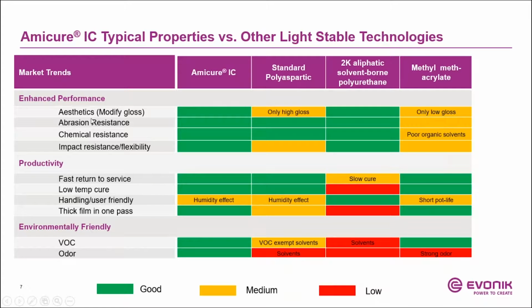So if you look at enhanced performance, one thing we talked about is aesthetics. And what we talked about here is modifying the gloss, getting the high gloss and low gloss. Polycarbamide technology, I have it in green. And in that case, because as I mentioned, you can vary the finish, high gloss and low gloss finish, similar to polyurethanes. You can do the same thing with polyurethanes through the addition of matting agents. I have the standard polyaspartic and MMA in orange, because they have a very nice finish. However, with standard polyaspartic, you generally get high gloss finish. With MMA, you only generally get low gloss finish.